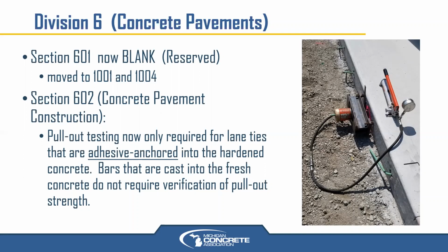Pull-out testing is only required for lane ties that are going to be adhesive anchored into the hardened concrete. So they drill the holes, blow out the dust, take a wire brush, clean out the hole, blow it again, insert epoxy into the hole, and then stick the bar in, and the epoxy flows out. You can use a cementitious grout as well. Most contractors choose the epoxy, and then allow the epoxy to set. And MDOT does require verification testing to make sure you do have proper pull-out resistance. So this test you'll see less of for those bars, and none where those bars are implanted into fresh concrete, only adhesive anchored. So that is a change from the current 2012 spec.